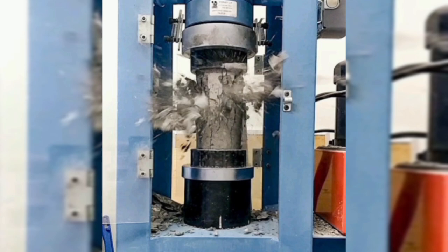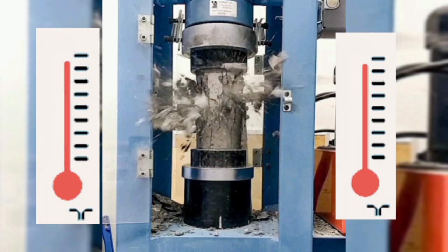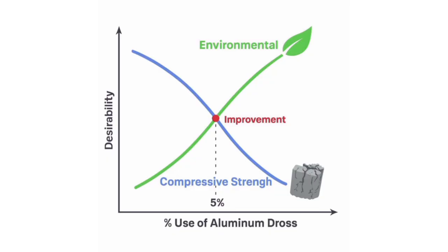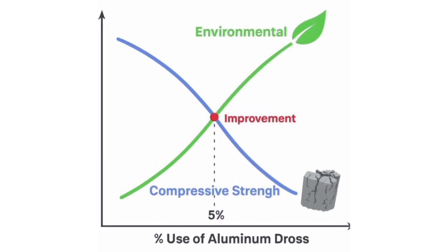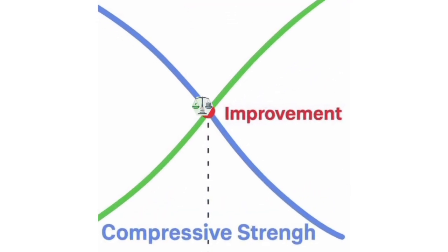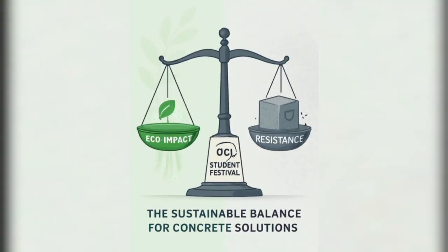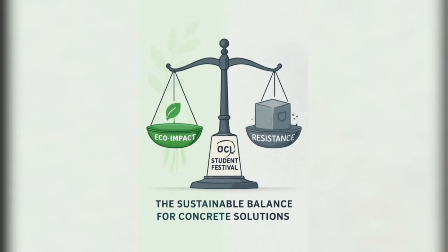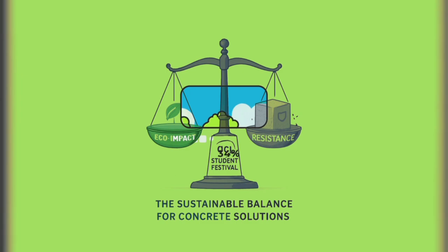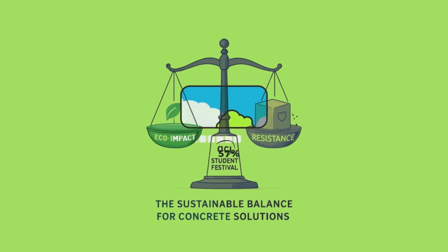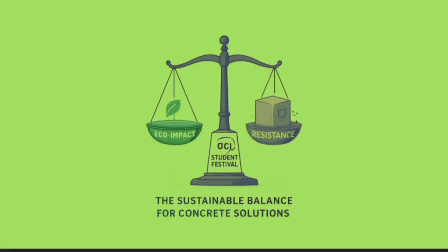According to research and experimental results, concrete containing aluminum dross performs better under high temperatures compared to concrete without dross, showing the least reduction in strength and the greatest environmental benefit. This approach reduces cement consumption, recycles industrial waste, and lowers the carbon footprint of concrete. The optimal point in our design is the percentage that achieves the least strength reduction and the greatest environmental saving, which is 5%